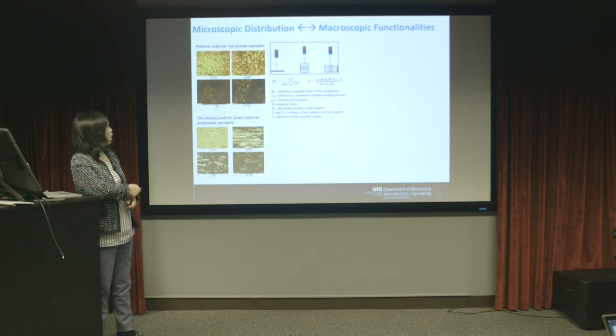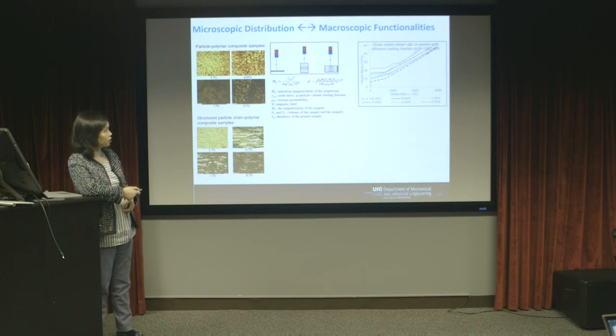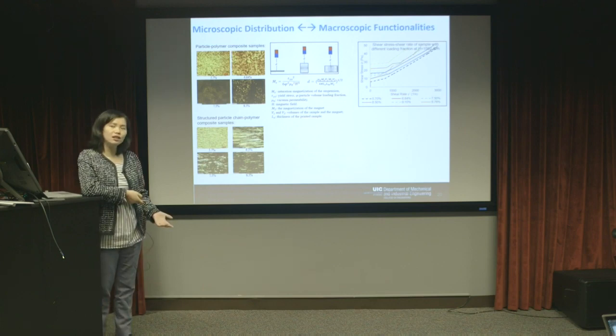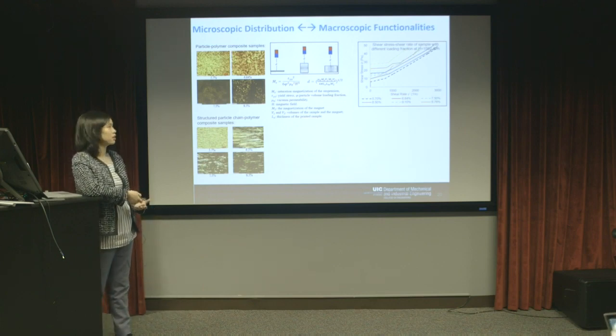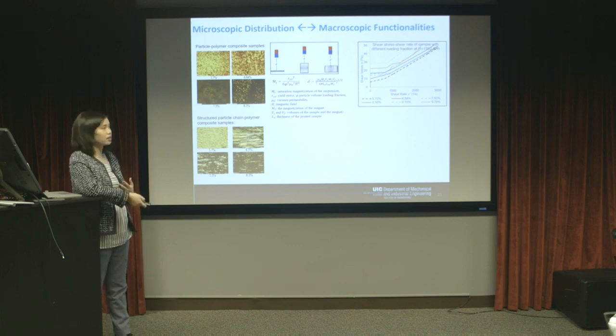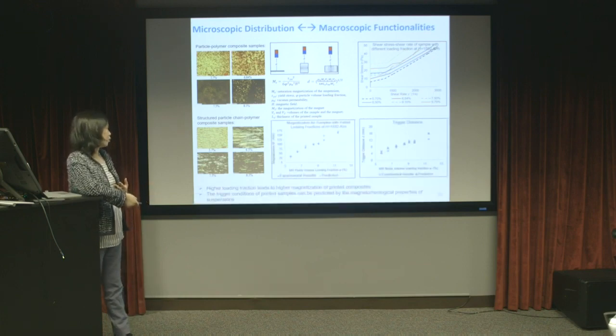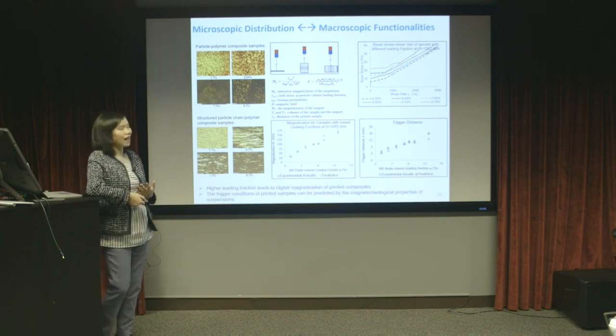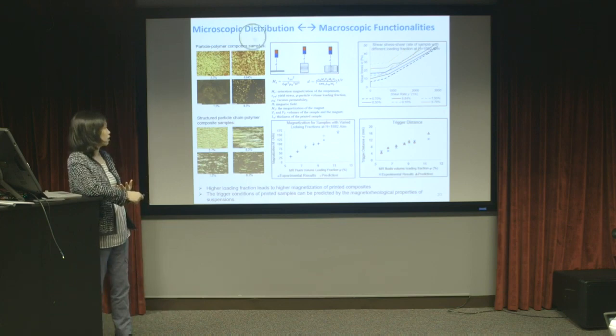Here I showed some microscopic images of the uniform composite and the level 1 unidirectional structural composite. And we can model the magnetic properties of those composites by considering the manufacturing process parameters, such as the magnetic field intensity that we used, and the material properties like the liquid viscosity and particle size. And we can predict some magnetic properties, such as the trigger conditions. Here, the trigger distance, D, is defined as the critical distance that you need in order to actuate a